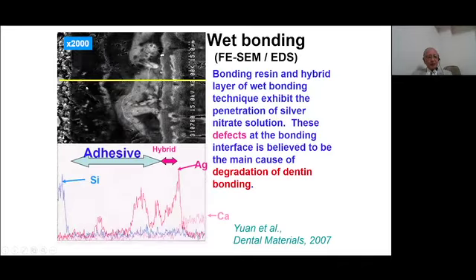This is the bond interface. This is the composite resin and bonding resin and hybrid layer and dentin. We immersed this specimen into the silver nitrate solution for one night. Then the silver penetrates into the microspace at the bond interface, and we try to detect the silver element on this scanning line. Now you can see the silver peak here.